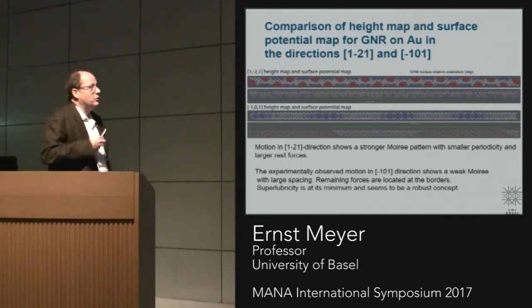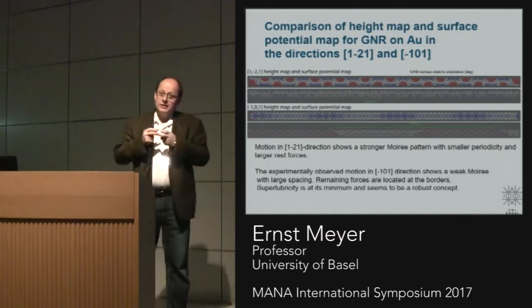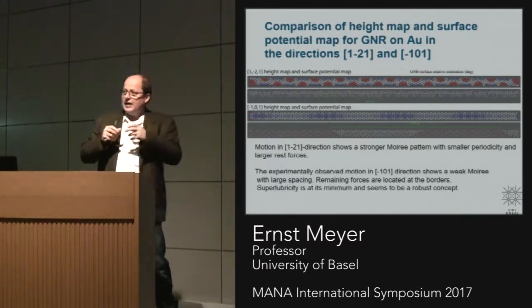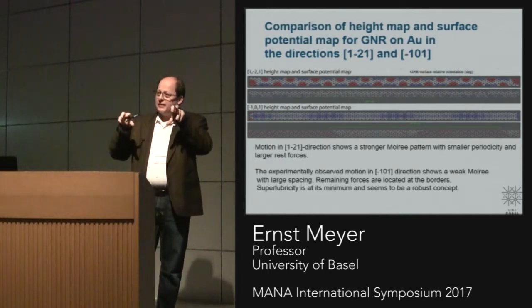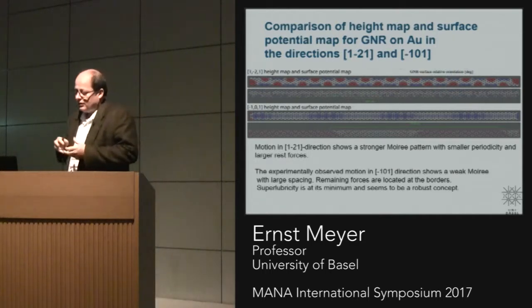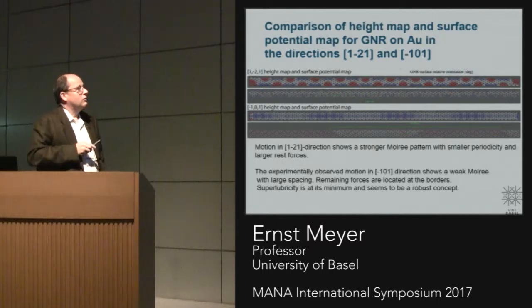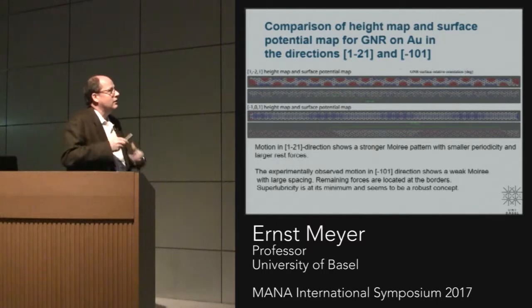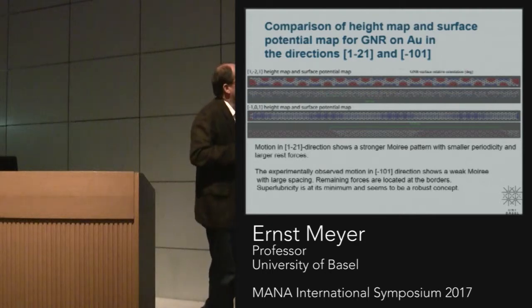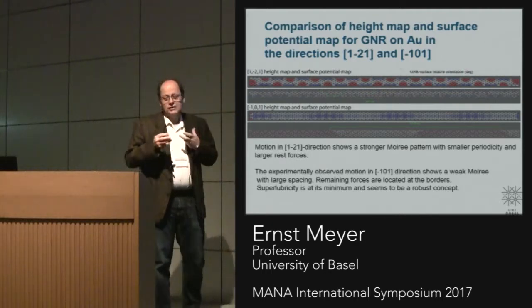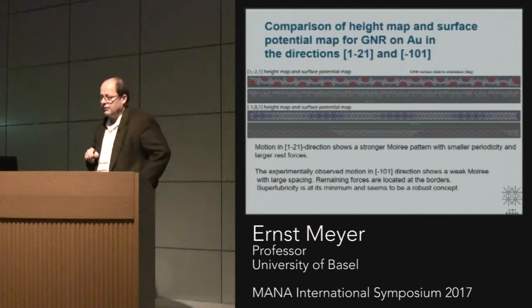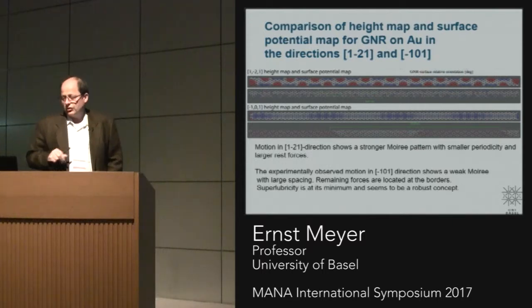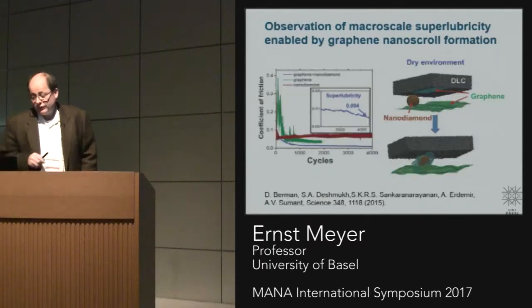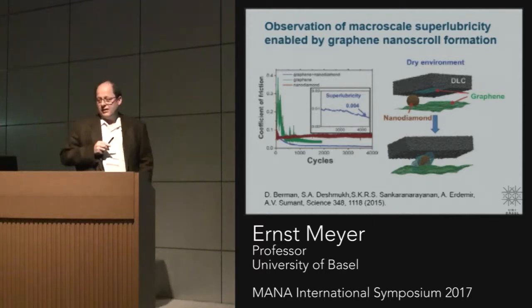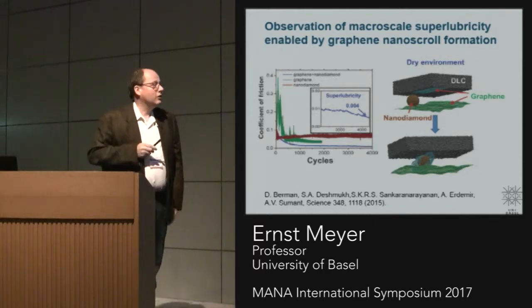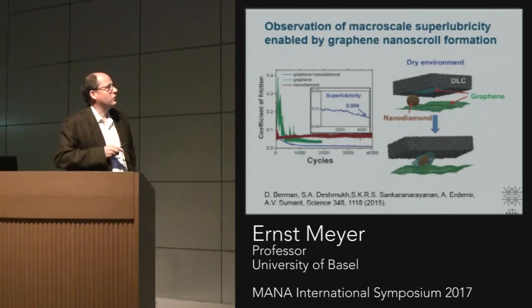And so we can say the special thing about nanoribbons is the high Young's modulus really allows that the lattice of the graphene stays more or less as it is, so it doesn't adapt to the substrate. So you can have nearly ideally this formation of Moiré type, incommensurable contacts, and that gives you these superlubric conditions. So now the question, of course, is can we use it, and also even for the real world, so to say, for the macroscopic world.